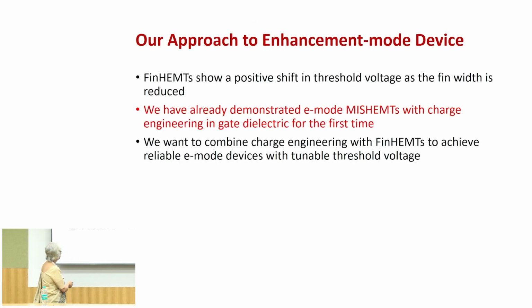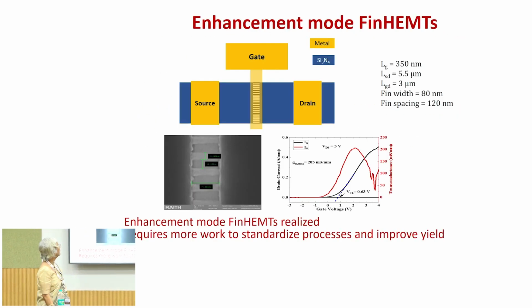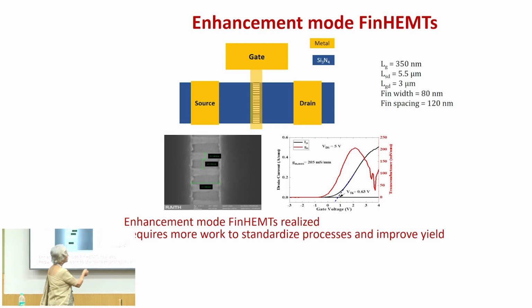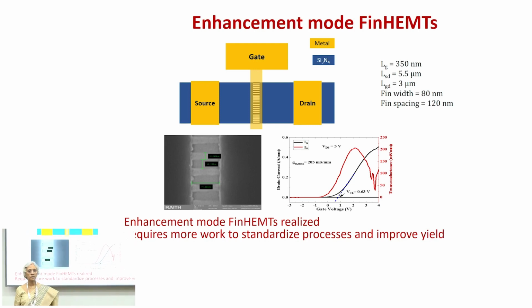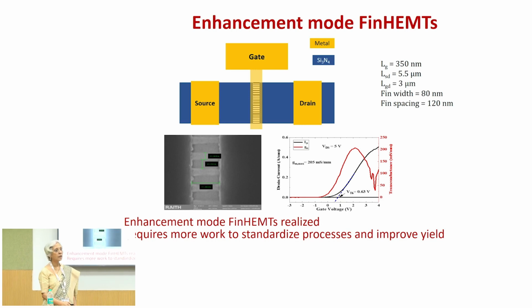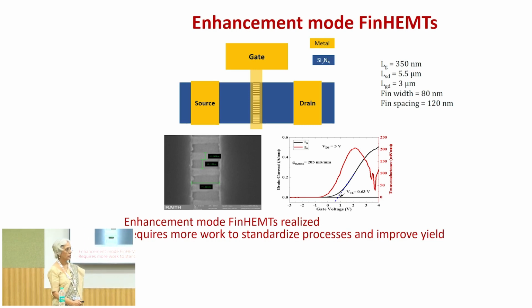So, this is what we have made use of, and now look at the enhancement mode FinHEMT that we have made. Here actually the fin width is reduced to 80 nanometer. The previous one, the fin width was about 100 nanometer. The gate length is 350 nanometer, and here if you notice, you find that the threshold voltage has now got shifted to plus 0.63 volt. So, it is actually a normally off device. So, it is possible to realize an enhancement mode FinHEMT by tweaking the geometry and going to a narrower fin width.